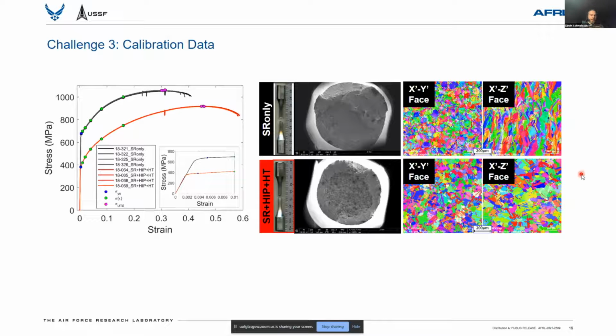In addition to characterizing the mechanical behavior, we also characterized the microstructure. As a quick pictorial description of that, I'm showing some electron backscatter diffraction maps of the grain structure interrogated on orthogonal planes in a region which is representative of the gauge. But we also provided a number of different quantitative descriptors of the microstructure.